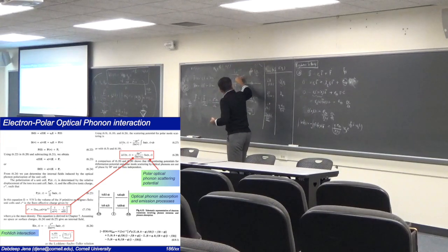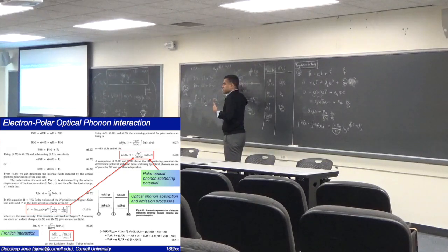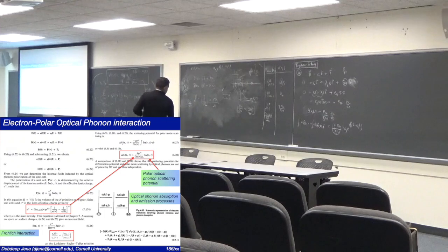As an example, in a ferroelectric, E star is the effective charge, and the distance between them is of the order of an angstrom. The charge here for a ferroelectric would be of the order of one electron charge, 1.6 times 10 to the minus 19. For gallium nitride, which is extremely polar, almost an ionic crystal, it is roughly 1 out of 100, or 5 out of 100. Gallium arsenide is like 1 out of 1,000 or less than that. Does that make sense? That's the charge, so order of magnitude, how polar things are.